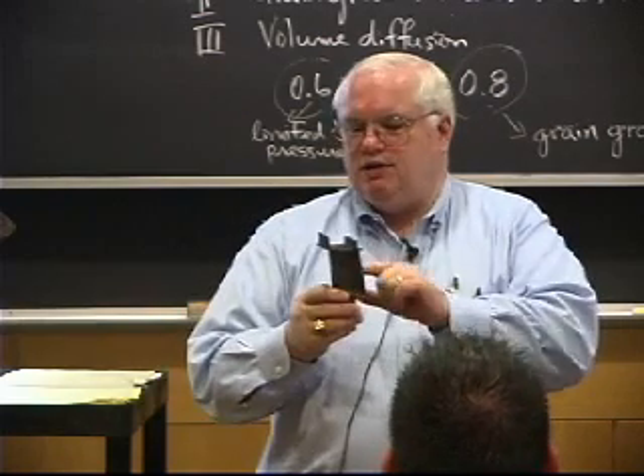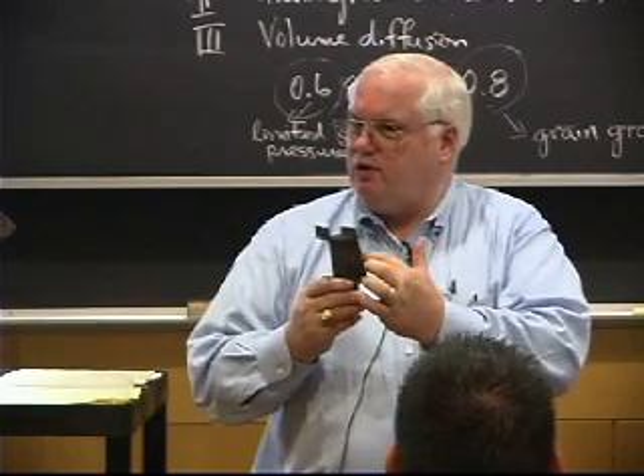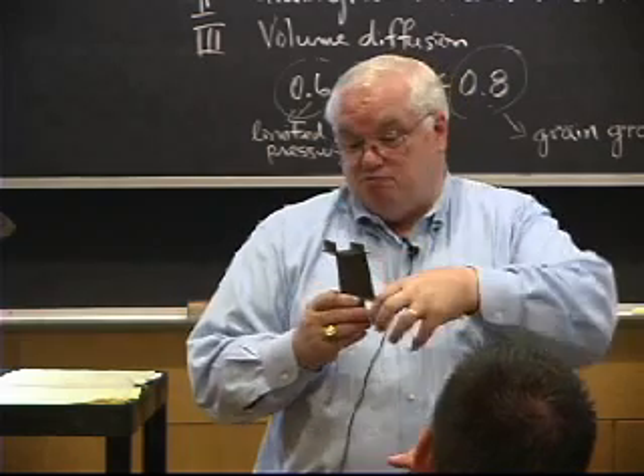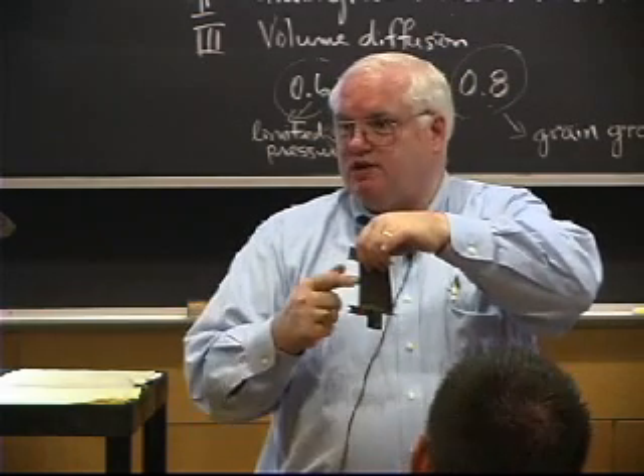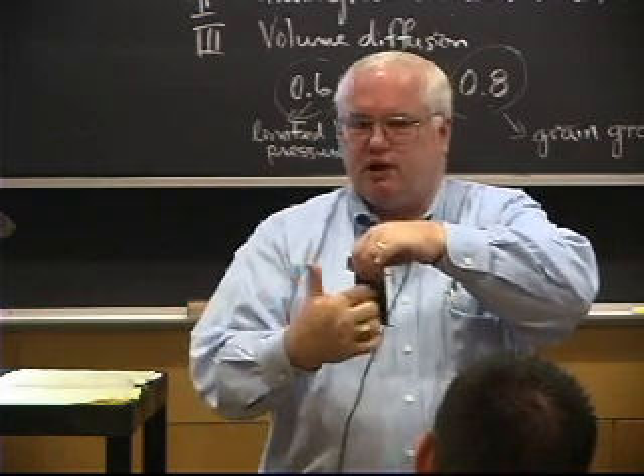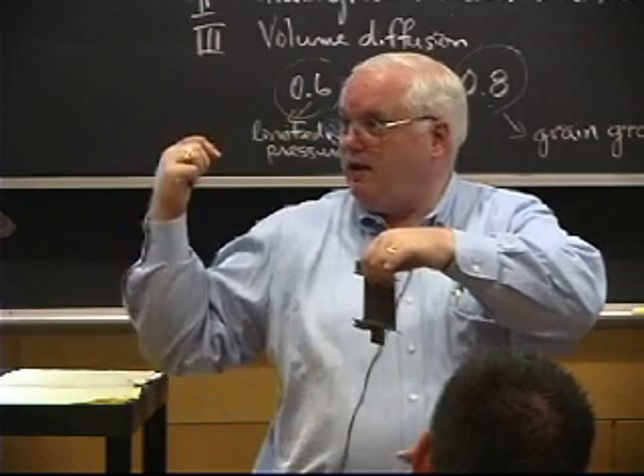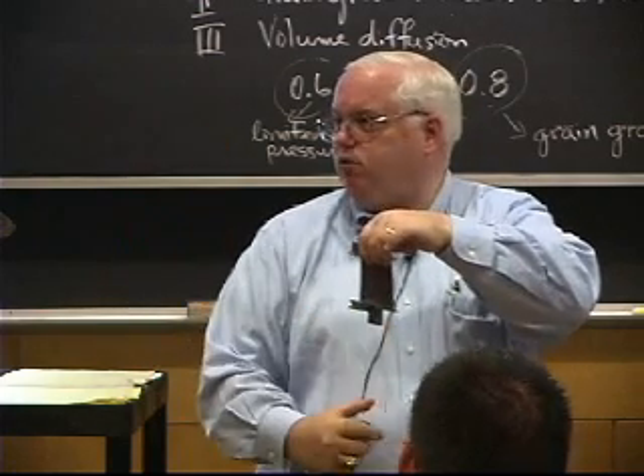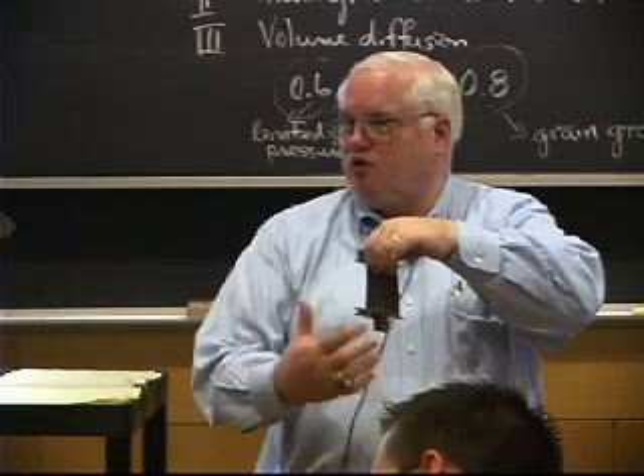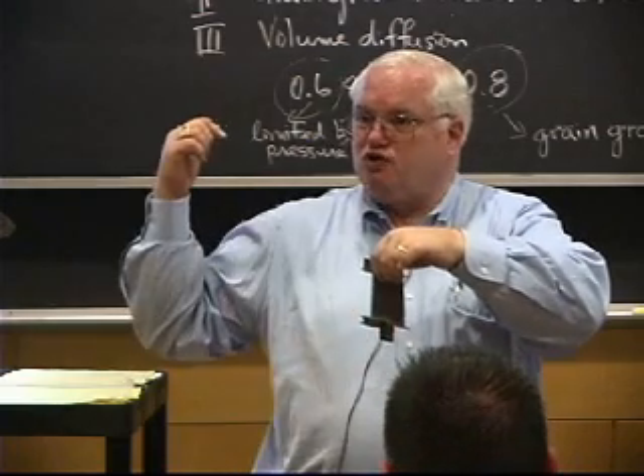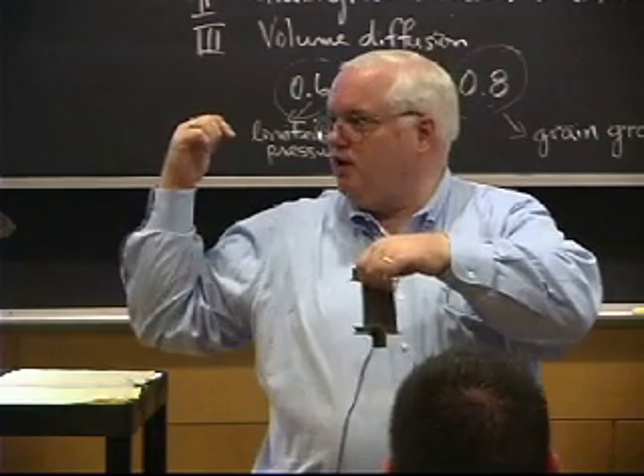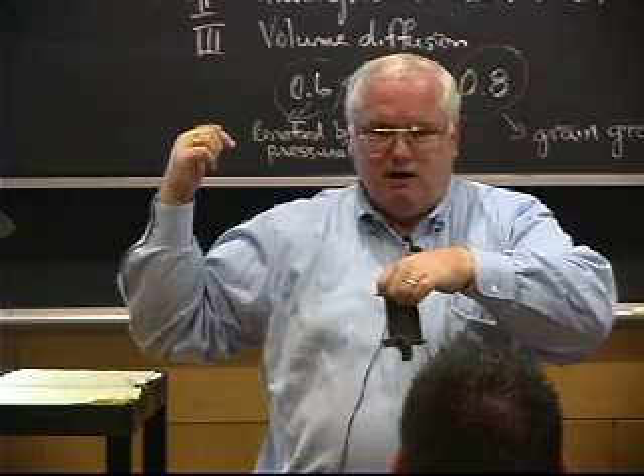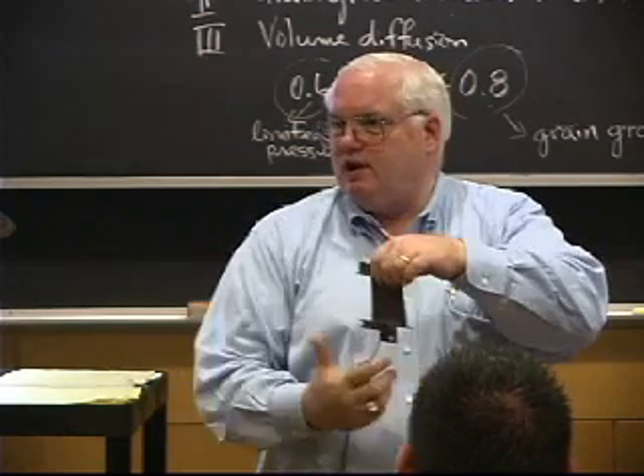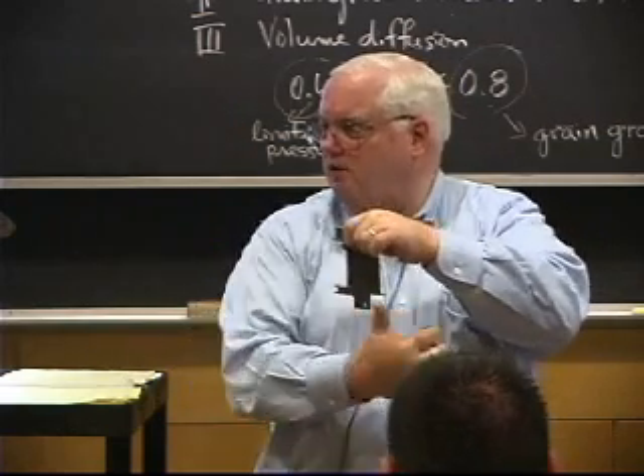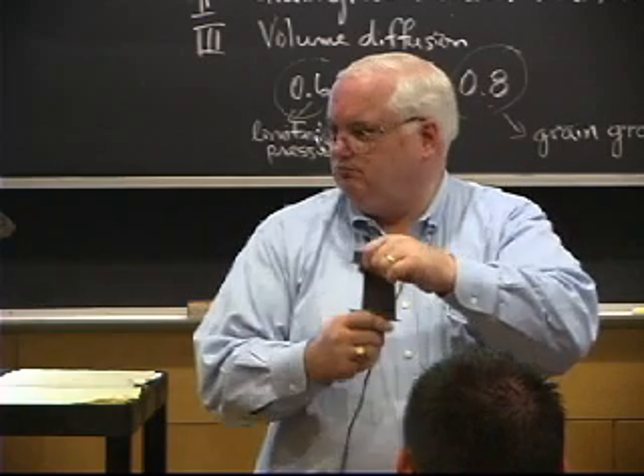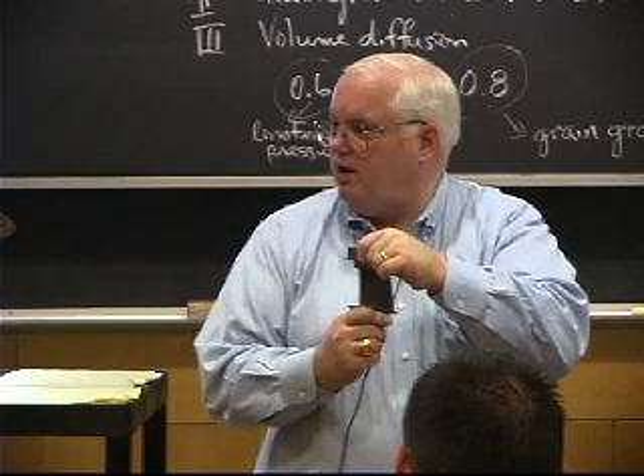And that's because the weakness at high temperatures is along the grain boundaries, okay? When you're pulling with stress on it, and you've got these grain boundaries, you can create vacancies because of that stress. We talked about annihilating vacancies. You can create vacancies if you apply a tensile stress. If you get enough vacancies, you'll start creating voids at the grain boundaries. Just like we're getting rid of them in diffusion bonding, you can create them. And you can perforate this thing, and the thing finally fails by failing along the perforated grain boundaries. You're just creating vacancies by applying a tensile stress.